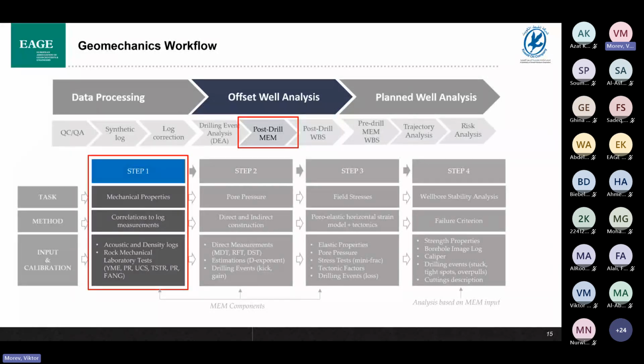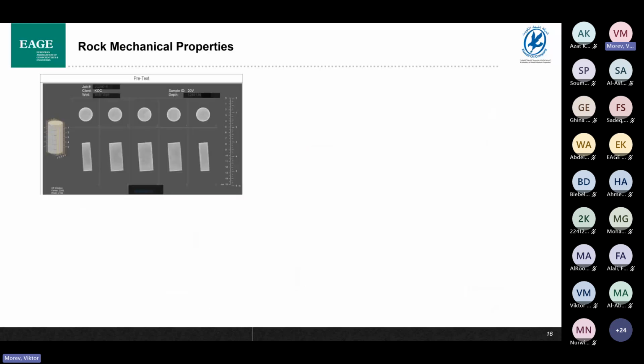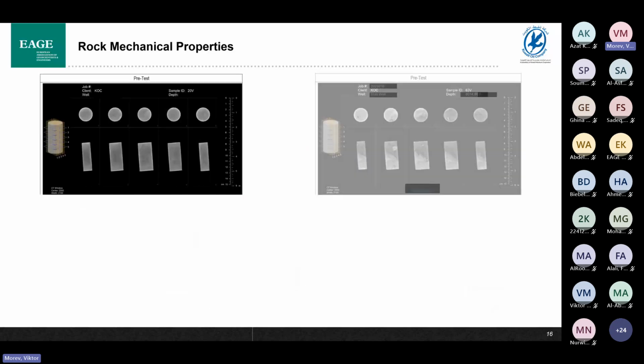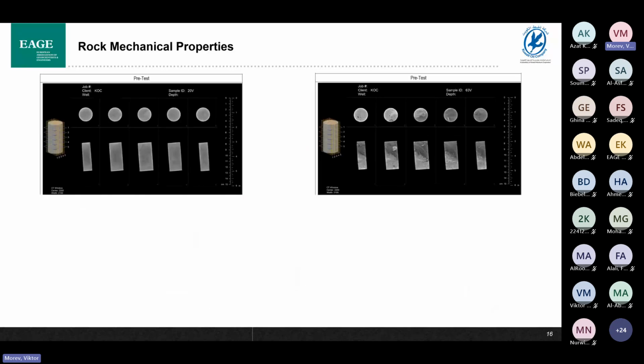So I would like to dedicate a couple of slides to the main laboratory testing techniques, starting with a very important step, quality control of the test results. Here you see the CT scans of core plugs before the testing. Eventually both plugs will fail during the test, but only one of them will pass our quality control.